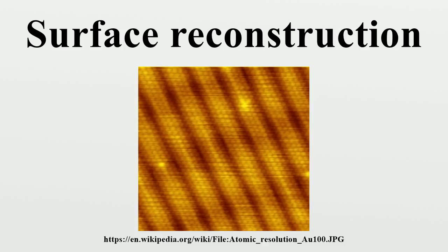This phase is not completely disordered, however, as this melting process allows the effects of the substrate interactions to become important again in determining the surface structure. This results in a recovery of the square structure within the disordered phase, and makes sense as at high temperatures the energy reduction allowed by the hexagonal reconstruction can be presumed to be less significant.